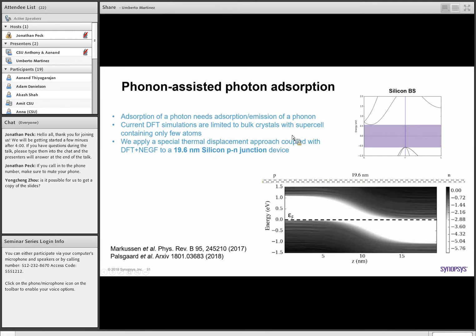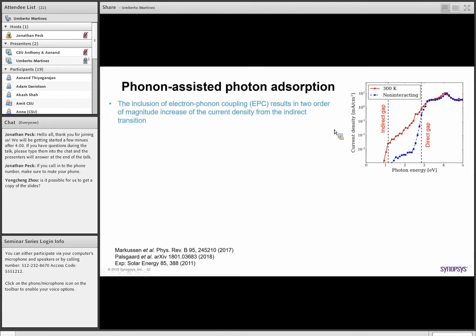So we apply here what we call the special thermal displacement approach to include this electron-phonon coupling, and we do that for a p-n junction device. We use that as a case study of about this size, and again you can clearly see the p-n junction. This is a typical p-n junction where you have p doped here, this is again the Fermi level, and n doped on this side, and we use this to study the photon energies and the current density as a function of the photon energy.